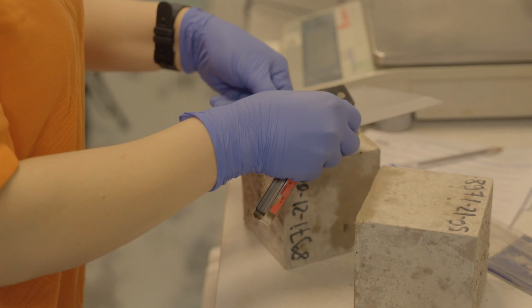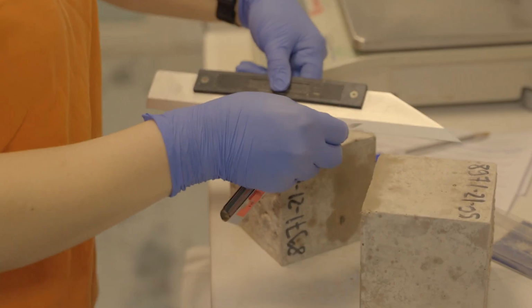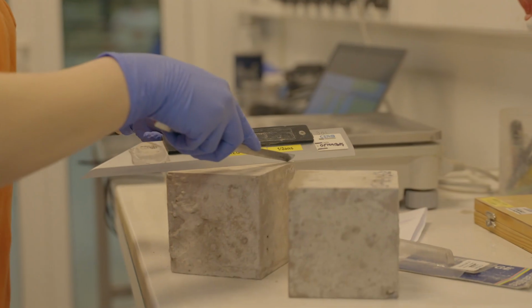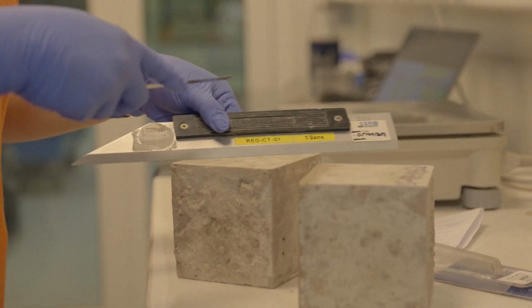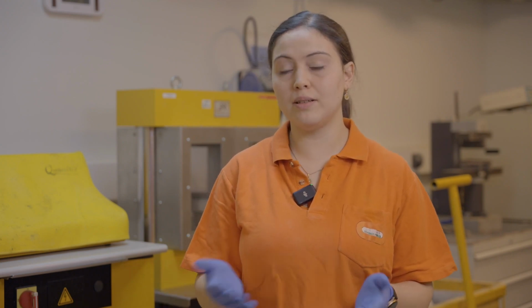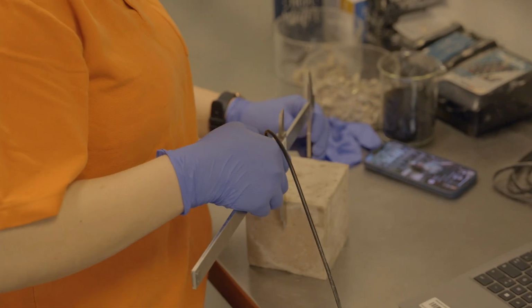Recently, I started working with foundry sands as a substitute for traditional sand. Foundry sands absorb a lot of water, and I was able to overcome this rheology limitation. By substituting up to 20% of the sand, I managed to achieve compressive strengths equal to or even higher than regular concrete.